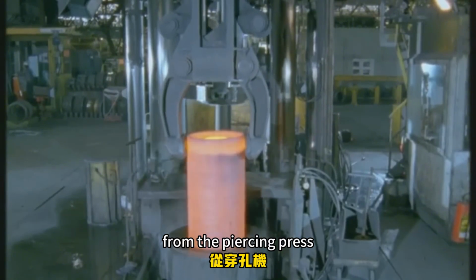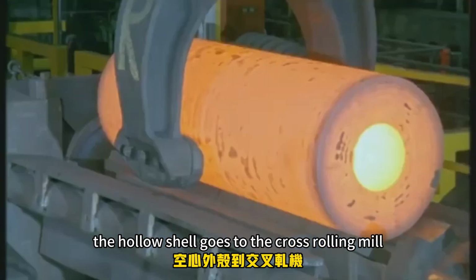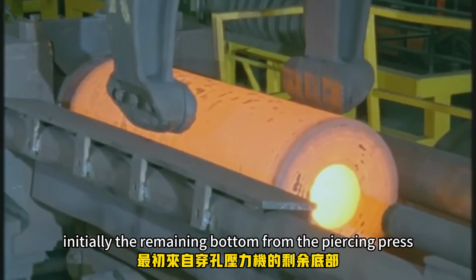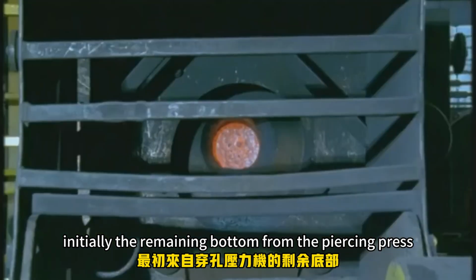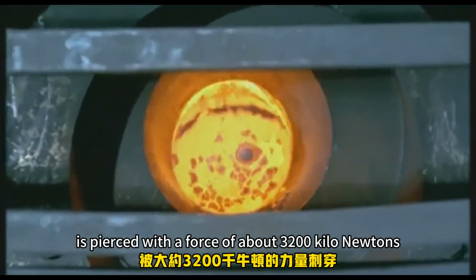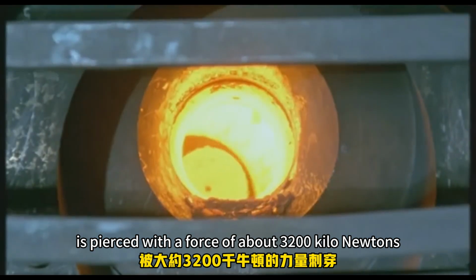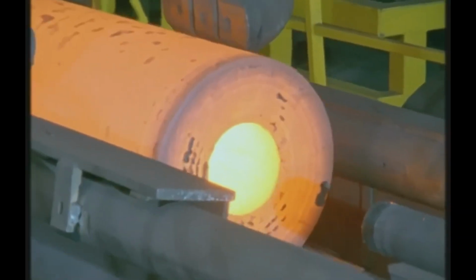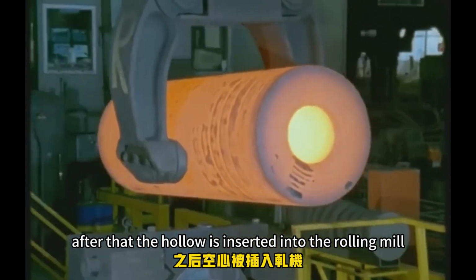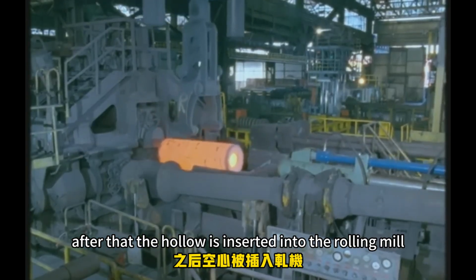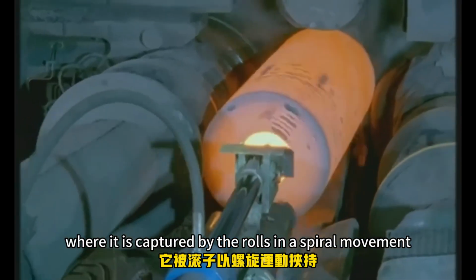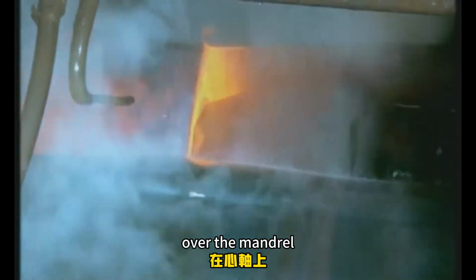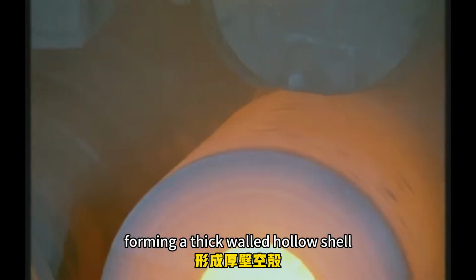From the piercing press, the hollow shell goes to the cross-rolling mill. Initially, the remaining bottom from the piercing press is pierced with a force of about 3,200 kN. After that, the hollow is inserted into the rolling mill, where it is captured by the rolls in a spiral movement over the mandrel, forming a thick-walled hollow shell.